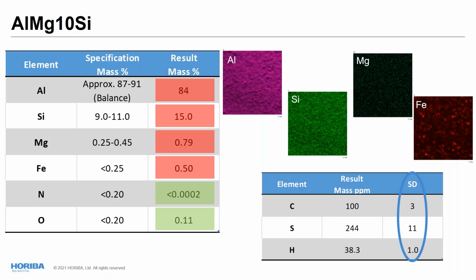For XRF, we are playing a little bit with the instrument and we perform some mapping. And you can see the different elements mapped over the powder, and you can see some obvious heterogeneity for iron with some dots that were more concentrated in some parts of the powder.